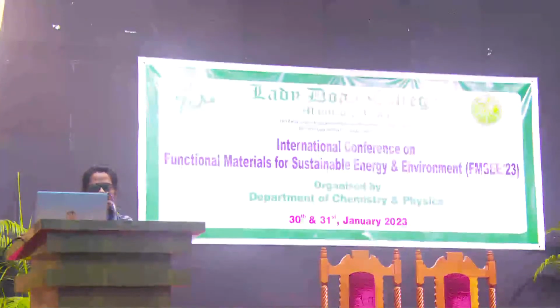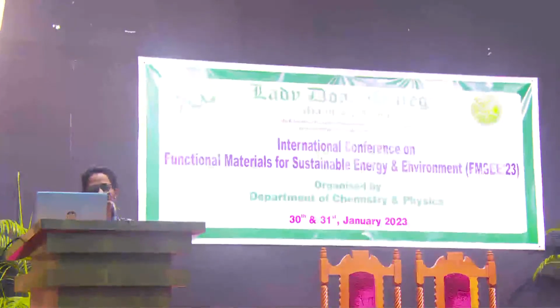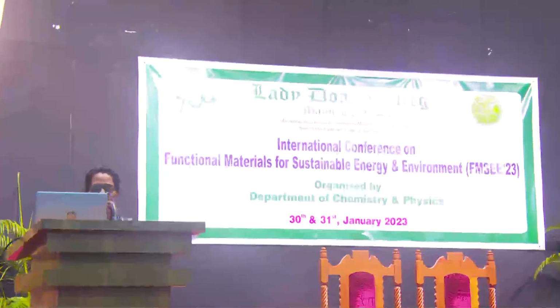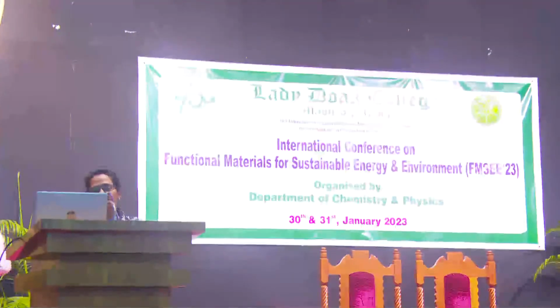Here, the preparation of copper barium tin sulfide nanoparticles was done by the hydrothermal method. Initially, the copper, barium and tin chloride precursors were taken in the ratio of 2:1:1 and 4 mole of sodium sulfide precursor was taken and mixed well in 40 ml solution, and kept at 230 degrees Celsius for 24 hours in a Teflon-lined autoclave, and the obtained precipitate was subjected to characterization. In the XRD result, the prominent peak I have observed is at the 110 plane.